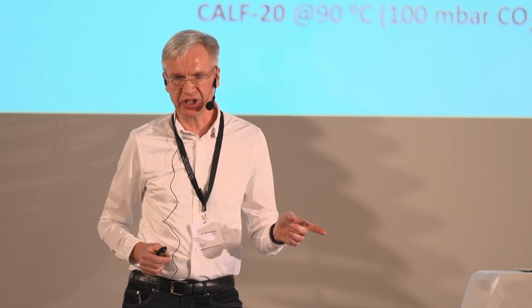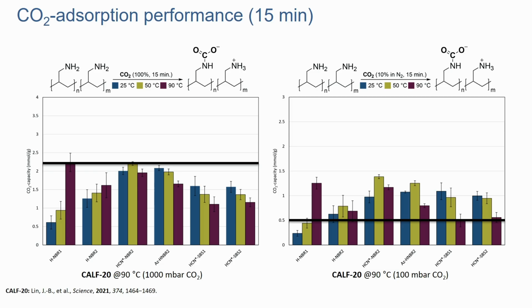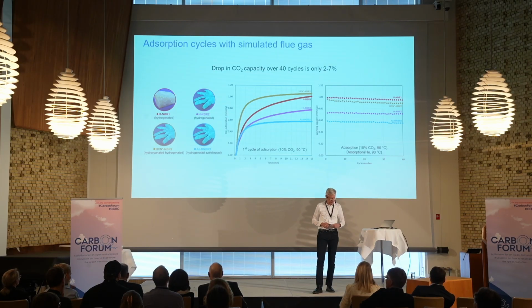But what is really cool is that if we start looking over a shorter time, 15 minutes, then our materials are competitive. The one on the left is 100%, but if we take flue gas conditions, 90 degrees, then our materials are even better than CALF 20. And I think this is really exciting for us. Anyways, I have to go through a bit faster. This is just to show the adsorption cycles, where we have pretty good stability of the materials.